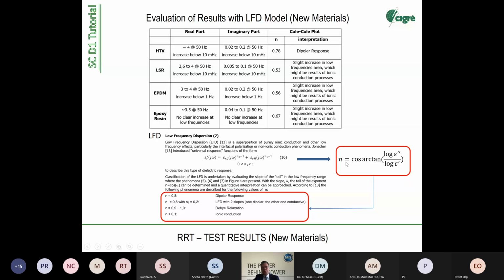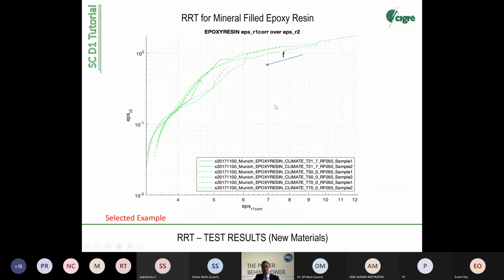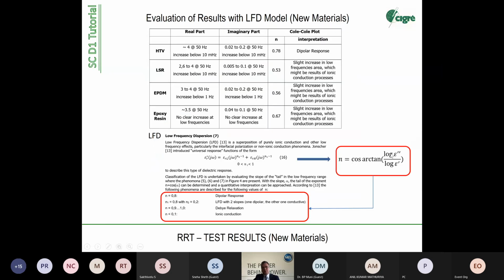And this N you have to see. N is actually, you have to make a straight line here, an extrapolation. Your software is also doing this, so you have to determine the angle of the slope, and from this angle, from this arctangent, you determine, by the cosine of the arctangent from these values in the logarithmic figure, you get out n. Stefan has done this by means of self-made computer software in order to have all diagrams under the same observation and under the same evaluation.